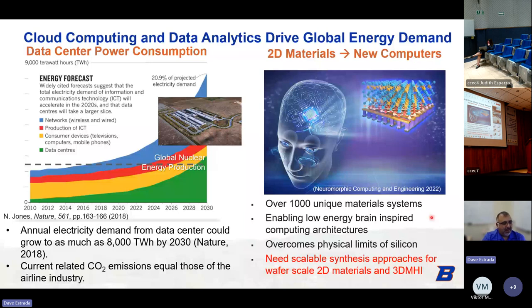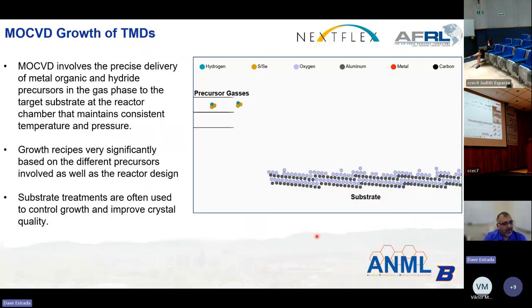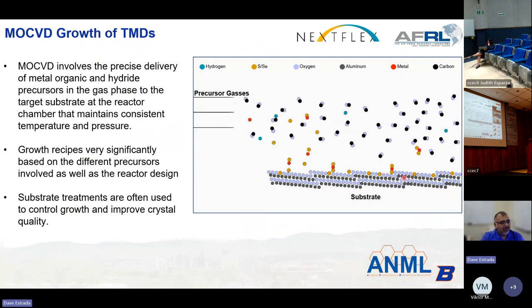So 2D materials are one path that the semiconductor industry is looking at to replace silicon and improve energy consumption by processors. So this needs scalable synthesis approaches to integrate 2D materials in a 3D monolithic heterogeneous integration fashion. So how do we get 2D materials to stack nicely on different dielectrics so that we can make multi-layer 2D ribbon FETs for processing applications? For that, we've turned to MOCVD, metal organic chemical vapor deposition, which basically involves the precise delivery of metal organics and hydride precursors in the gas phase to the substrate.